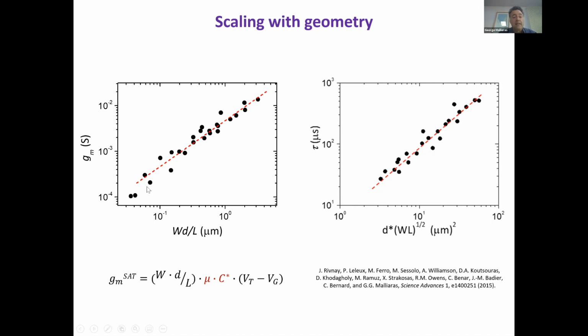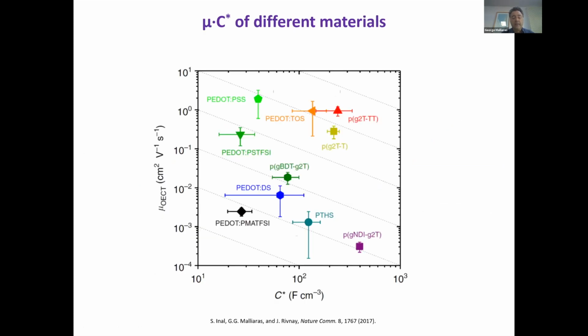And you can capture this behavior by this simple model. You also can capture the time behavior of these materials. You can understand very basic transistor type of characteristics using a very simple model. Not only that, but this provides a mechanism to classify different materials based on mobilities of electronic charge and volumetric capacitance. And we make this plot where the better materials lie up on this top right corner. And this has guided the synthesis of these materials in the field. And currently there are materials that exceed the performance of PEDOT:PSS in these devices.